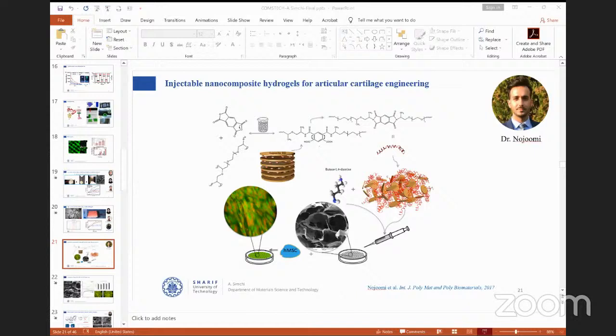The next step, we tried to do some work on cartilage engineering. As you know, cartilage in tissue engineering is very difficult because the chondrocyte cells are difficult to regenerate. I had a student who said to me, I can make a special polymer and hydrogel specifically for cartilage. And he used polyethylene glycol and terminated the end functions with amine groups. And then added laponite, a two-dimensional inorganic material, inside, and then loaded the cells, stem cells, inside, in order to regenerate the cartilage. It is really ambitious research because, first of all, the mechanical properties are important. Second of all, it should be injectable because we don't want invasive surgery for cartilage repair, and it also has to make a platform for regeneration by stem cell therapy.